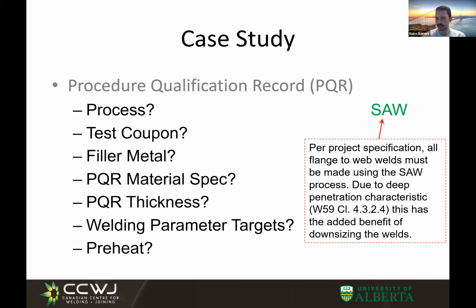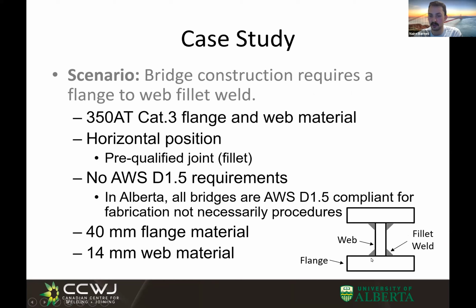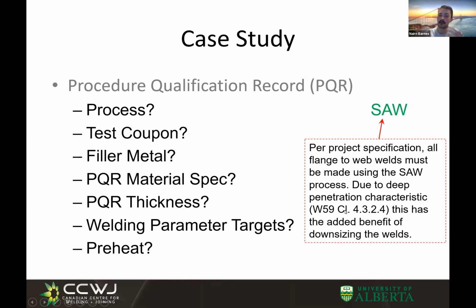So when we're building these procedures, we want to typically be very, very efficient, or as efficient as we can be. So in this case, we're going to select sub-arc welding, because sub-arc welding can be run by a machine and it can be automated. You can literally stick a tractor into this joint and run it the entire length of this girder in one shot. And because sub-arc is such a large heat input and high deposition process, you're able to deposit your required weld in one pass. And one of the interesting things that's considered by the Canadian Welding Code is that because sub-arc is this type of process, you get an extra 2 millimeters.